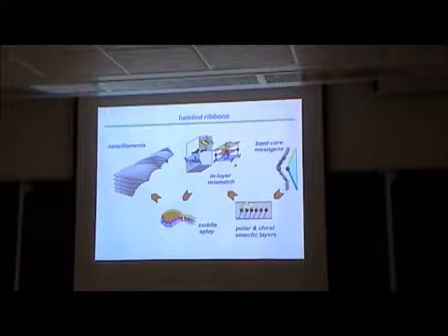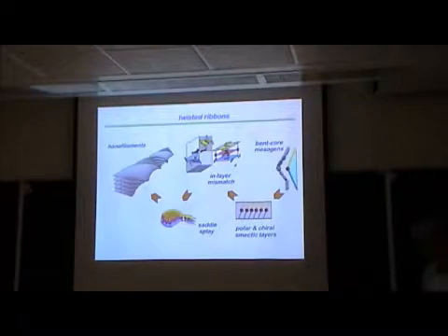Because in a layer, the top half of the molecule is tilted in the east-west direction. The bottom half of the molecule is tilted in the north-south direction. So when you take those two stretched things and try to put them together, they pop into a saddle splay. And so this local structure, when the phase grows in, forces this growth as a filament. If you try to make the filament bigger, then the layers get flatter, and that suppresses the phase. So this is a self-limiting growth form that is stabilized by this tendency for saddle splay.